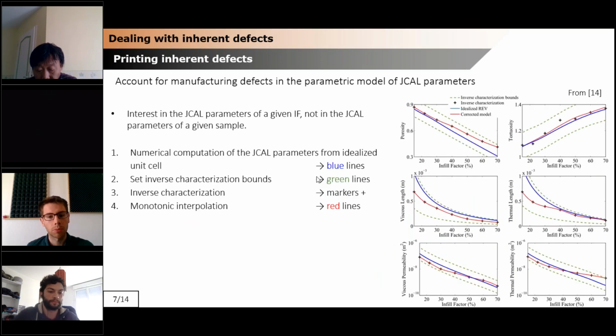So in this way, you can obtain the acoustic parameters of the microlattice for different lattice constants. So what we did is that first we computed from the idealized unit cell the variation of its acoustic intrinsic parameters, for porosity, tortuosity, and so on, with respect to the infill factor, so with respect to the lattice constant. So we computed them from the idealized unit cell, so here are the blue lines. Then we set some inverse characterization bounds, so the green lines.